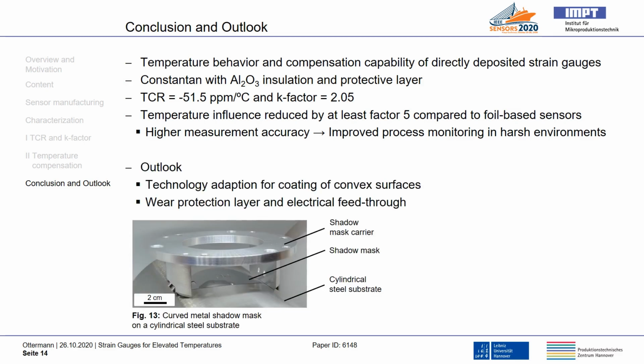At the moment, we're working on the technology adaptation for the coating of convex surfaces. If we look at figure 13, we can see our new approach. We use a curved shadow mask out of stainless steel, which is held by a shadow mask carrier. This system is pressed against the cylindrical steel substrate, which will be the bottom hole assembly later.